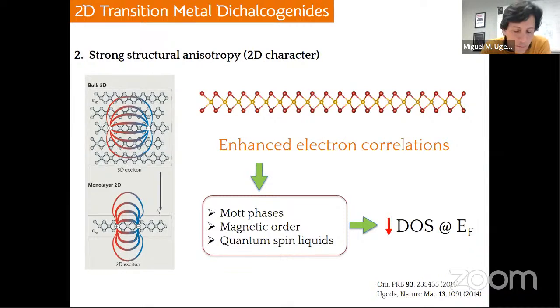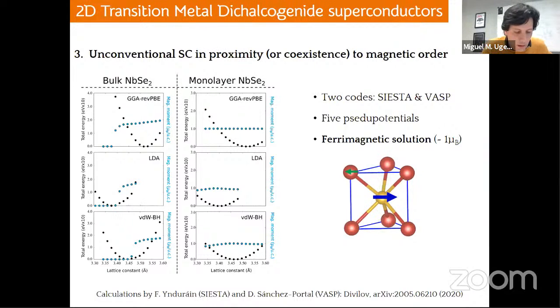But there's another consequence of this, which is that all of these many-body phases in general have a tendency to diminish the density of states at the Fermi level, which is not beneficial at all for conventional superconductivity. And finally, these materials seem to be also close to a magnetic state. We know this nowadays because of 2 works. The work by Professor Felix Yndurain at the Universidad Autónoma de Madrid. He studied in collaboration with Daniel Sanchez Portal here at the CFM, using 2 different codes, Siesta and VASP, the ground state for bulk niobium diselenide and monolayer niobium diselenide. And it turns out that no matter the code that they use, no matter the pseudopotential that they use, the monolayer seems to have a ferrimagnetic ground state, as you see here.